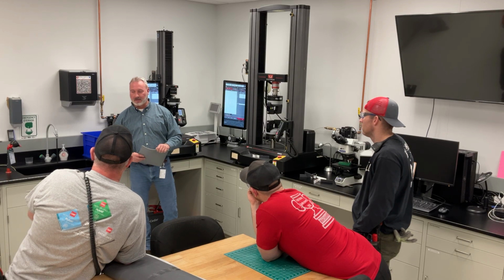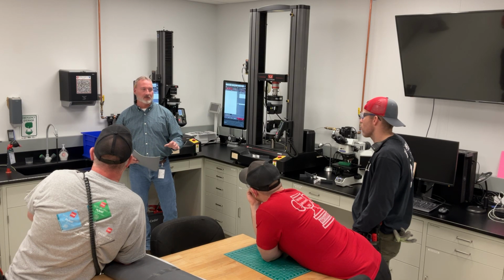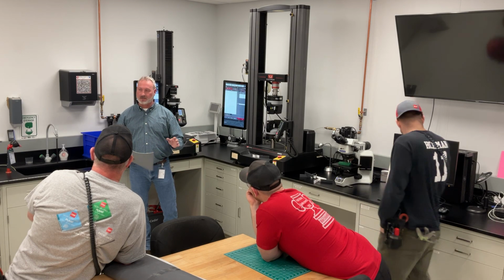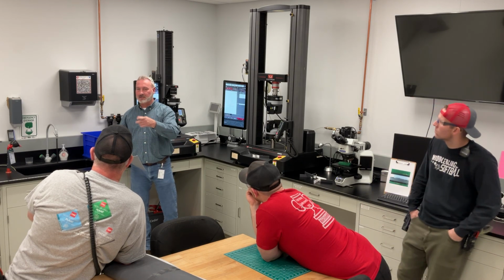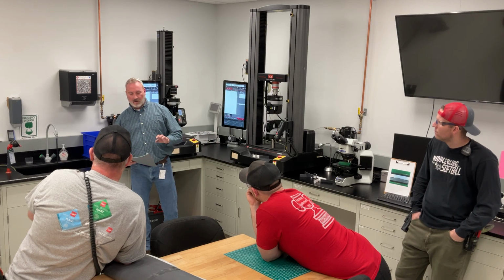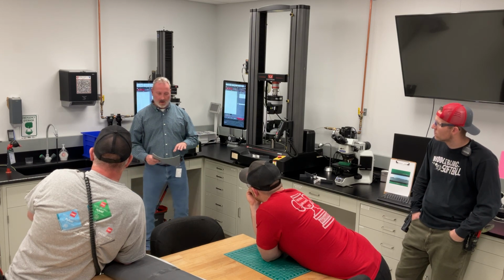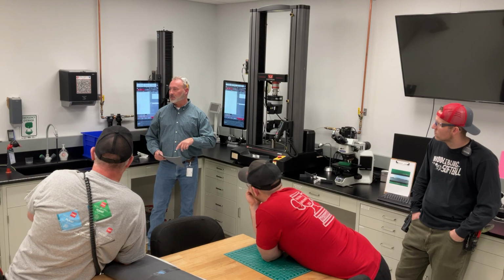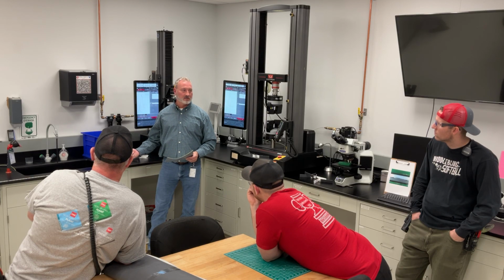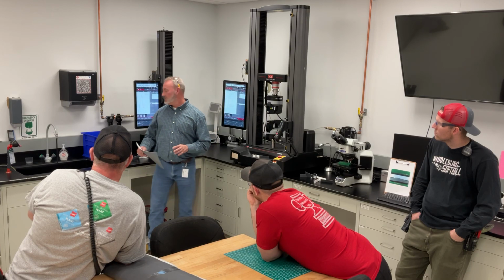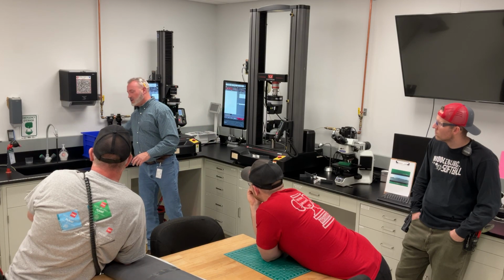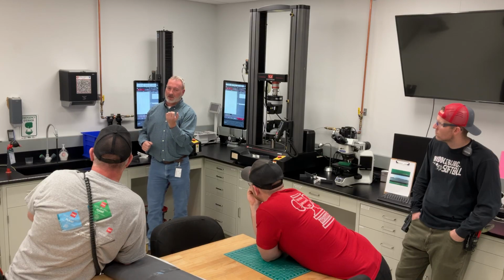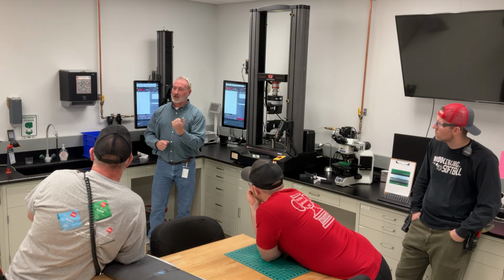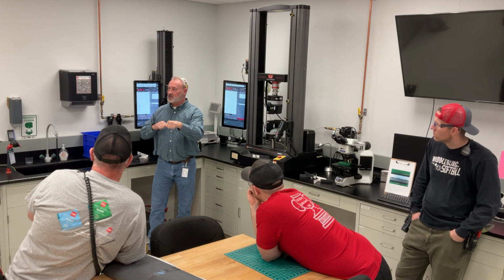Sometimes machine direction bounces around the spec. It's pretty close. Cross direction, we never have an issue with. And the funny thing about tears is the thicker the product, the worse the numbers. So a 45 mil will outperform an 80 mil in that test. Because the 45 mil and the 60 mil have a tendency, as it starts to tear, to twist on itself, and when it does that, it causes a little more tension. Whereas the 80 mil holds its shape, and you just tear it like a piece of paper.